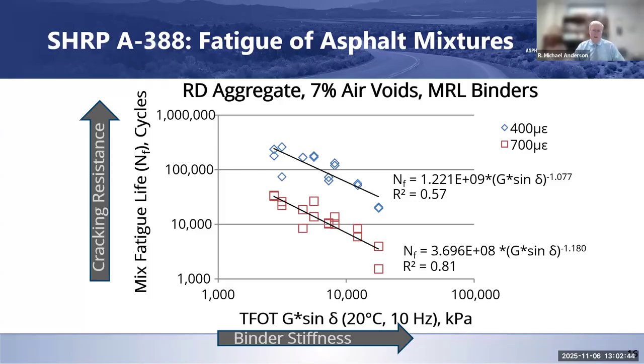Yeah, it's a good point. One of the things that just kind of previewed that both the 9-59 and somewhat the 9-60 research is looking at is having two parameters at intermediate temperatures. And I think part of that comes from the fact that we have to recognize that cracking at intermediate temperatures really is complex. It's more than one thing. And if you're trying to mitigate against that, it really matters whether you're talking about fatigue cracking or whether you're talking about, I'll use the phrase durability cracking, but it could be weathering, it could be loss of ductility, whatever you want to call it. Those are kind of different things.